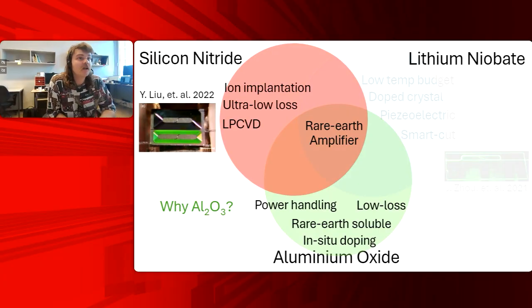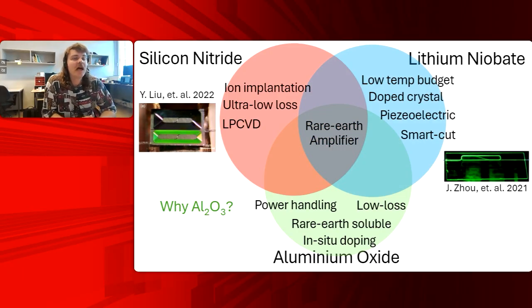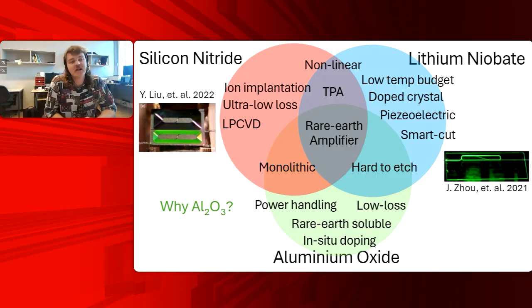In comparison, lithium niobate has also been doped with rare earth ions. However, its material has a low temperature budget, and therefore you have a limited choice of the cladding material which you can put on top of these devices. They rely on doped crystals. However, they're inherently piezoelectric and rely on smart cut technology to form the wafers. Not all of these are exactly drawbacks, just showing an overall comparison. As I said, no insult if you're interested in these materials yourselves. There are some drawbacks, of course, to aluminum oxide. It's hard to etch, just like lithium niobate. It can be done though. However, it can be done monolithically and has this linear operation, which lends itself very well to amplification, as I'll show you guys.